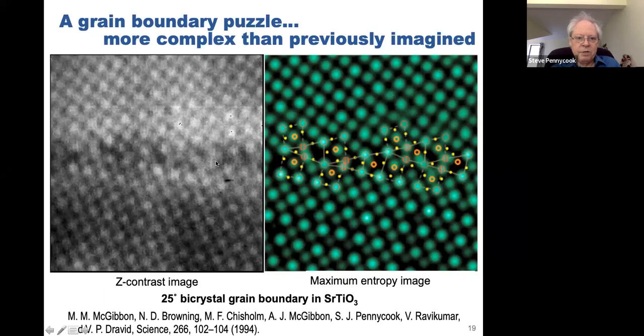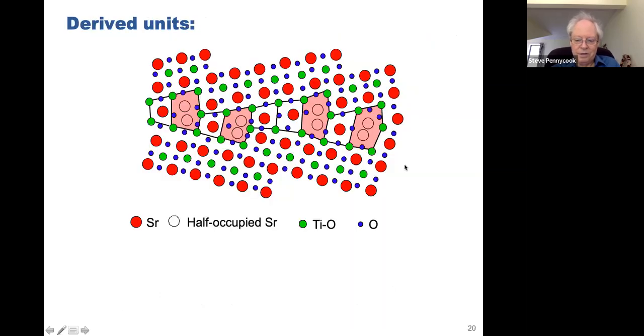When you had a phase contrast image, you would build various models and see which model matched the experimental image. Well, in our case, we just took a Z contrast image, and it's very easy to see these columns. This is sharpened up a little bit with maximum entropy. Of course, in those days, we couldn't see the oxygens, but we could see the cations and distinguish the strontiums from the titaniums. And the structures we saw at the grain boundary were not like any of the previous models. And so that's where we got this often applied phrase, structure was more complicated than previously thought.